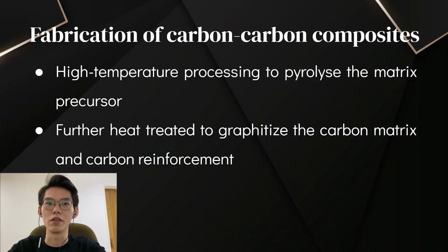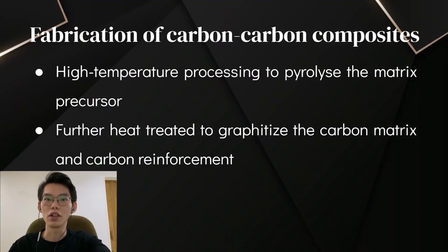Hi, my name is Loo Ji Yu. Fabrication of the composite involves high temperature processing to pyrolyze the matrix precursor or for the reaction of gases to form the carbon matrix in a chemical vapor deposition (CVD) process. The composite can be further heat treated to graphitize the carbon matrix and carbon fiber reinforcement. Through graphitization, it chemically and thermally stabilizes the composite for use at high temperatures.